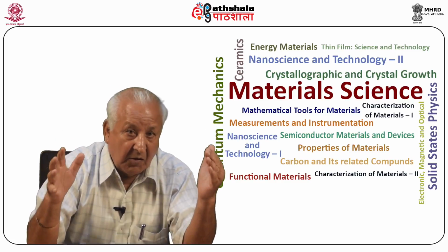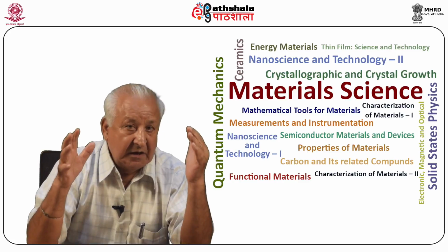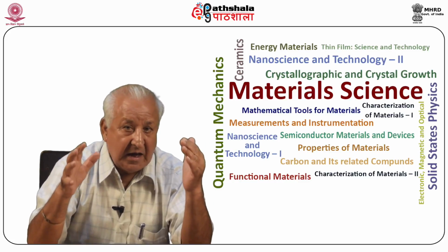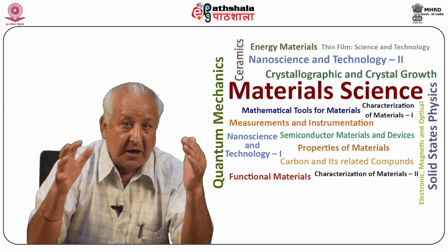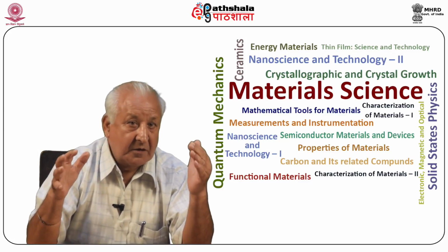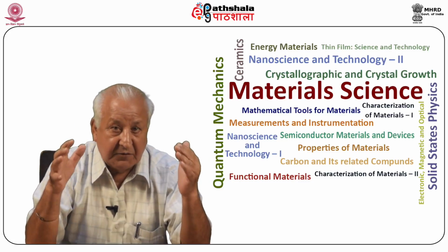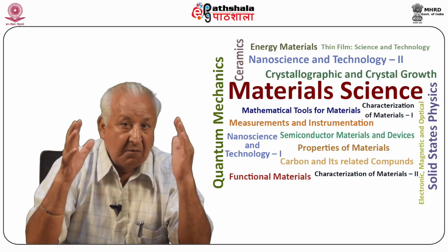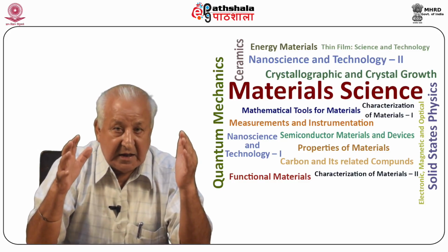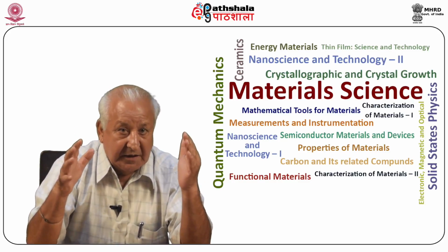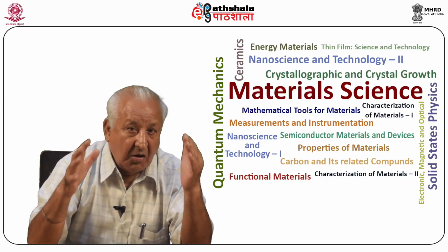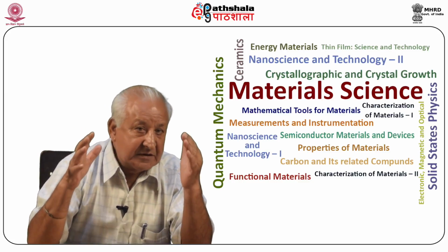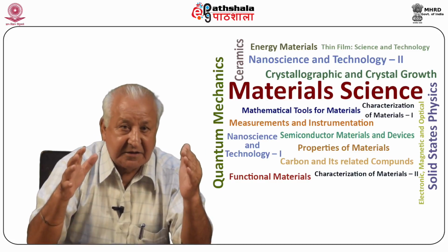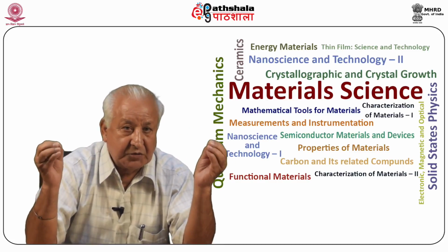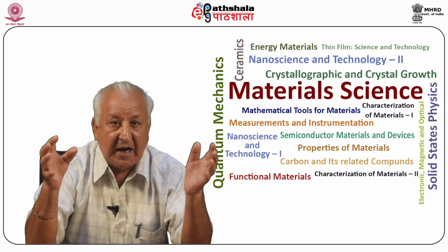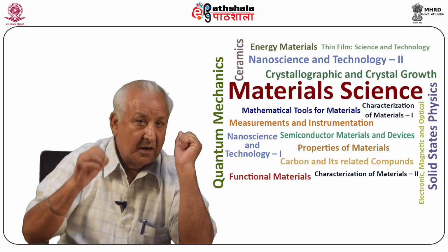The electron involved in this process is referred to as KL2L3 Auger electron, which carries energy equal to EK minus EL2 minus EL3. It is again characteristic of the atom from which it is released, and as such these electrons could be used for identification and analysis.